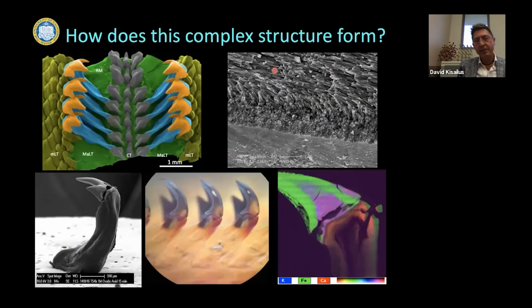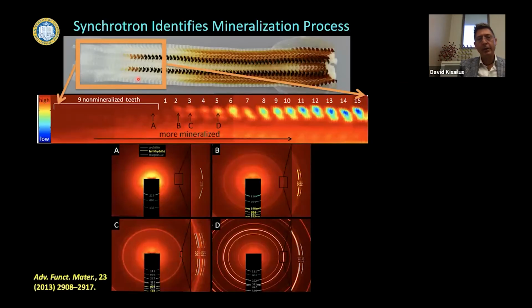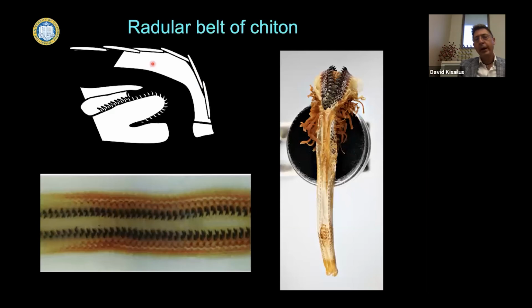So how do these teeth actually form? We've gone in at the early stages of the radula and looked using synchrotron, and we find, knowing that the fully mineralized teeth are made of magnetite, early on, the organic that's present here is an alpha chitin, but the first mineral phase that we see, the orange and the yellow and orange here, is ferrihydrite. That will eventually transform to magnetite just within one or two rows of teeth. So how does that happen?